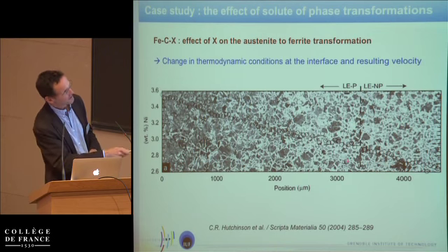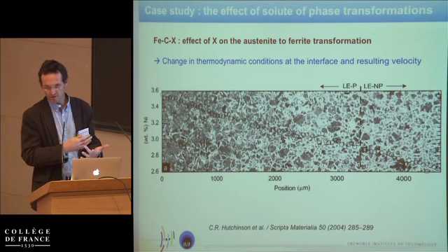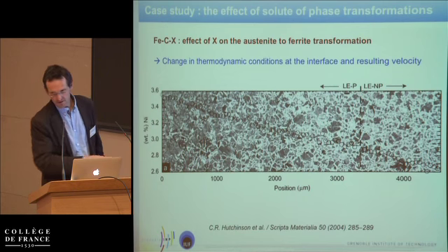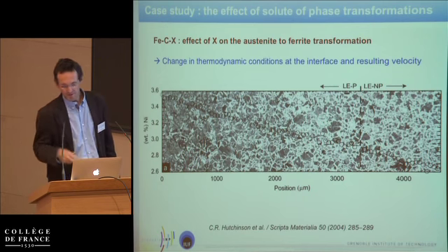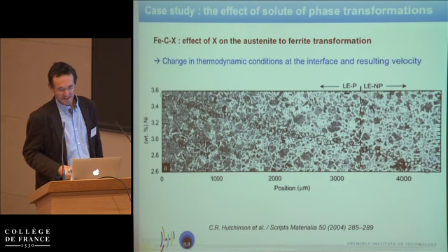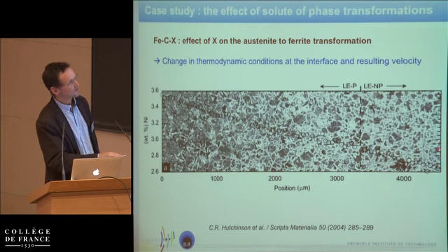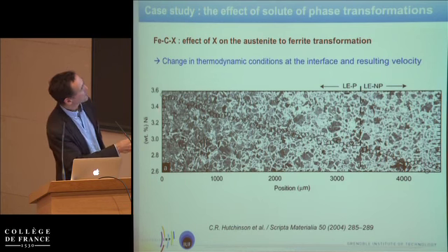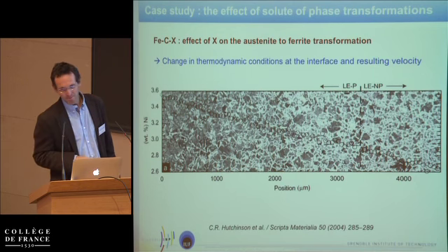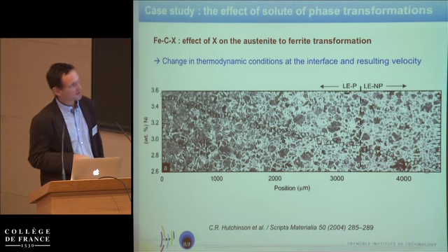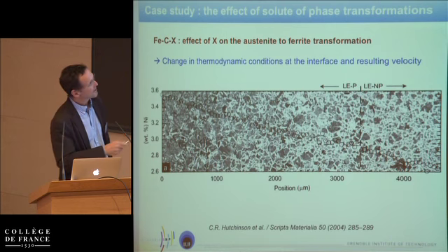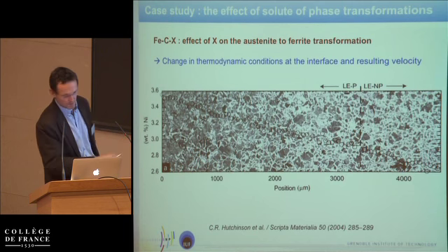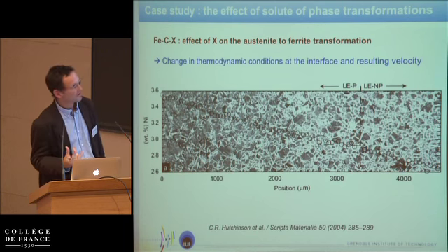And you can decide, depending on the microstructure that you could watch at a higher resolution with another tool, what was the boundary between the two thermodynamic conditions. So here it's typically a microstructural control alloy design to know, okay, if you want fast or slow kinetics of your transformation, you can put the chemistry either at 3.4 or 3.2%. This would have been quite difficult to show with different alloys, because the difference in content here is quite small. So to do that with individual alloys is quite difficult.